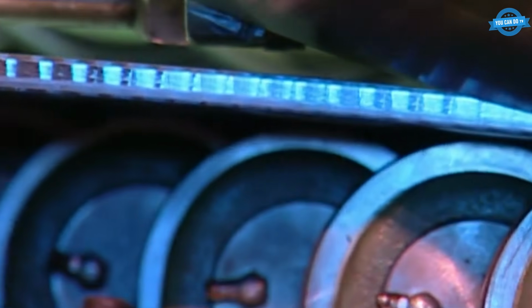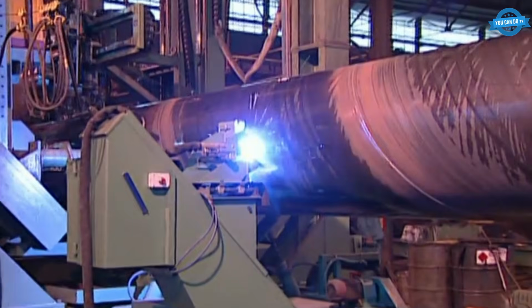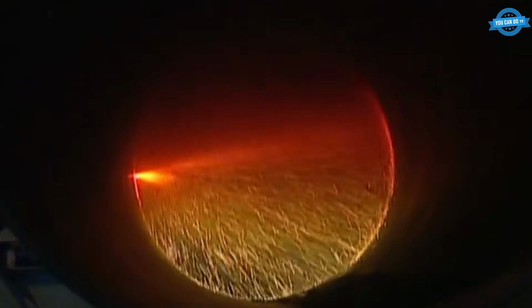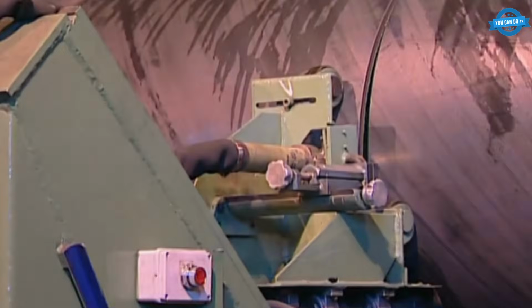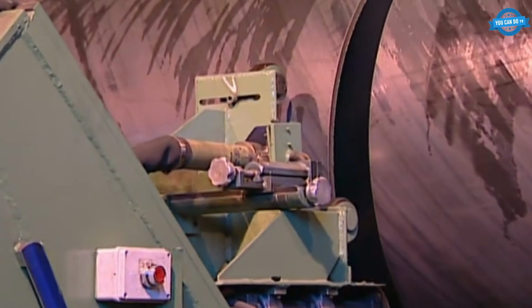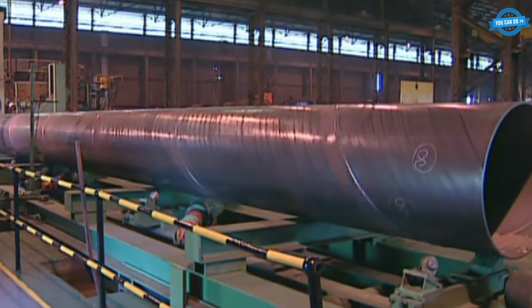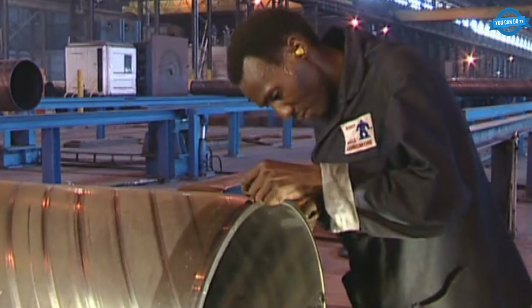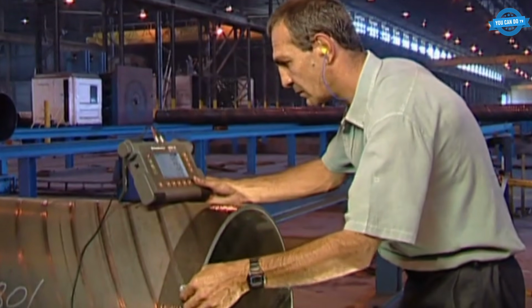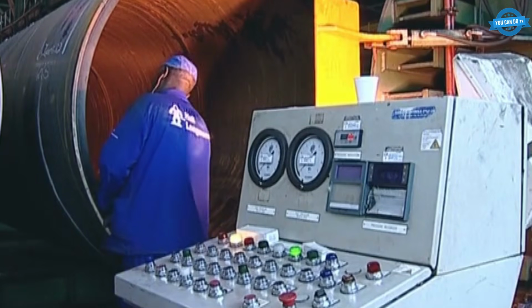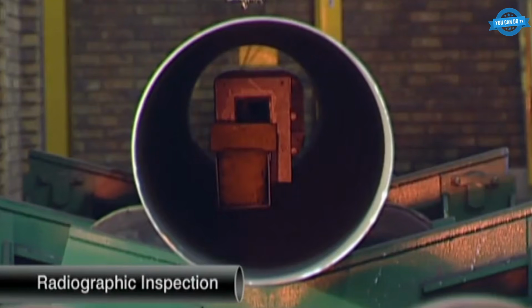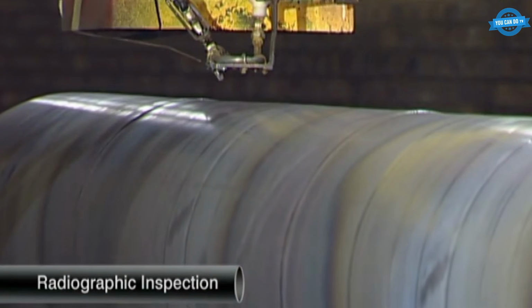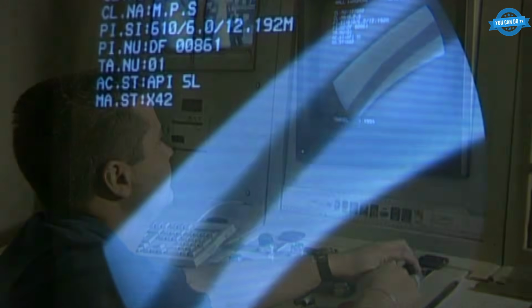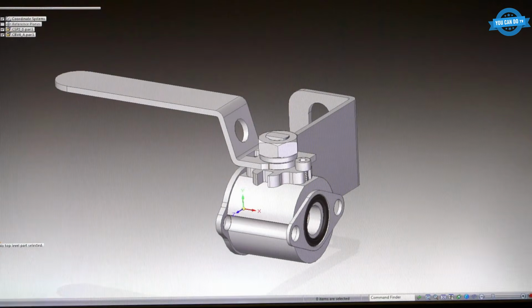The strip is helically wound into a tube shape, and 5 electronically controlled welding heads apply internal and external beads simultaneously. Strip gap alignment is precision controlled to ensure full weld integrity. After cutting, each pipe undergoes ultrasonic testing, hydrostatic pressure testing, and full-length radiographic inspection to confirm a weld factor of 1.